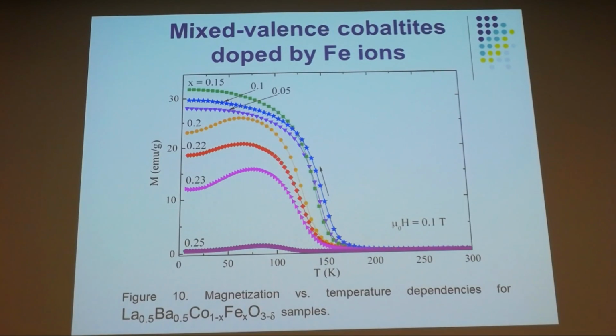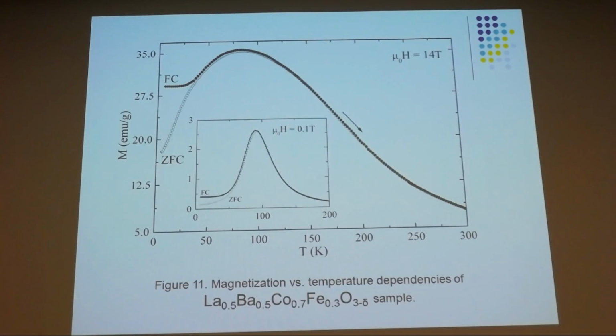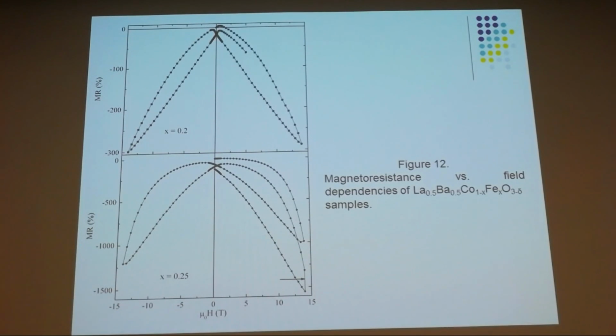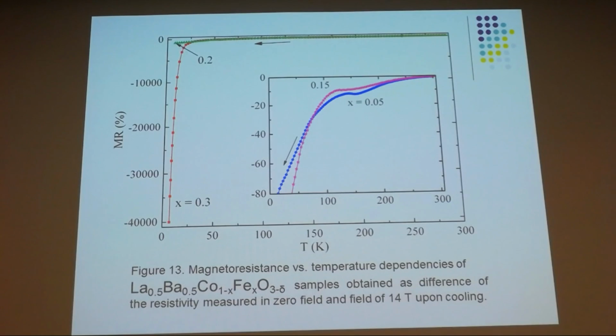Mixed valence cobaltite doped by iron ions. Under iron doping, magnetization gradually disappears. There is a peak of magnetization in heavily doped compounds. But standard cobaltites are metallic both in the magnetically ordered state and the paramagnetic state, and do not exhibit large magnetic resistance. However, magnetic resistance in iron doped cobaltites is very large, and observed at low temperature.